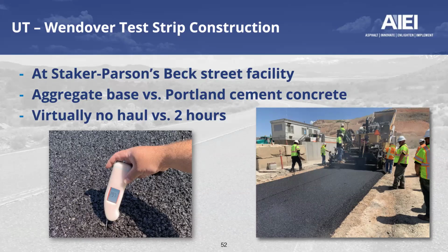They placed it on top of what really is an unprepared gravel surface. They simply brought a blade in, broomed off the loose material after it was bladed smooth, and then laid this thick lift at 7.5 inches, uncompacted, to be compacted down to a full 6 inches.